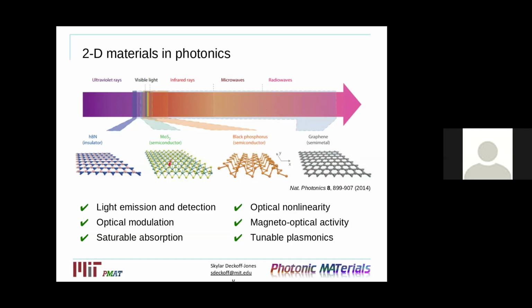However, within each material, you also have additional tunability by controlling the thickness. Traditionally, a 2D material is a single layer, but oftentimes within the 2D materials community, you're looking at few layer thicknesses or even approaching tens of nanometers to hundreds of nanometers, in which case you're transitioning to that bulk regime. And through the control of the thickness, you get an additional handle to tune the size of the band gap. So this is really promising for light emission and detection. However, the 2D materials, because there's a large array of them, have demonstrated other great properties for optical nonlinearities, various modulations, saturable absorption, even magnetic properties as of recently.